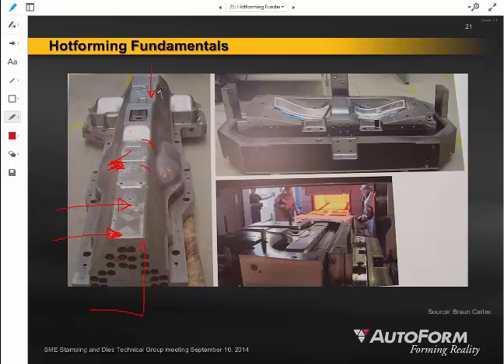What's really interesting about hot stamping for me is this range of temperatures we're talking about. We're talking about material just at its austenitization temperature, and then we're bringing it down to, when it's leaving the die, somewhere between 80 degrees Celsius and 200 degrees Celsius. So it's just a broad range of temperatures that whatever sensing, whatever equipment we're using has to be flexible enough to behave properly through such a wide range of calibration environments.